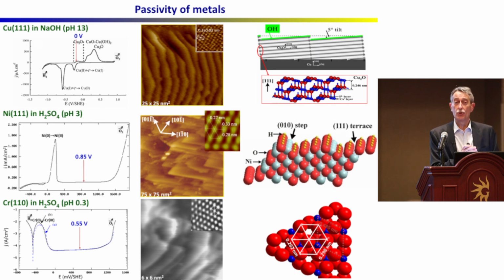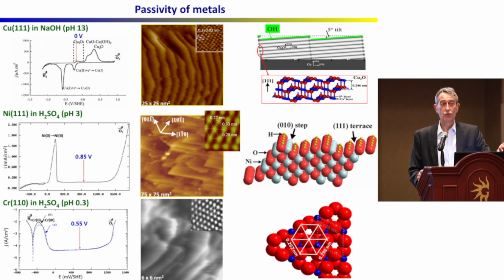And this is exactly what you need to optimize the position of atoms at the interface. So again, nature is doing that. We don't have to do it by processing the surface. This is done naturally. So crystallinity and epitaxial growth and interface energy minimization is already observed here.